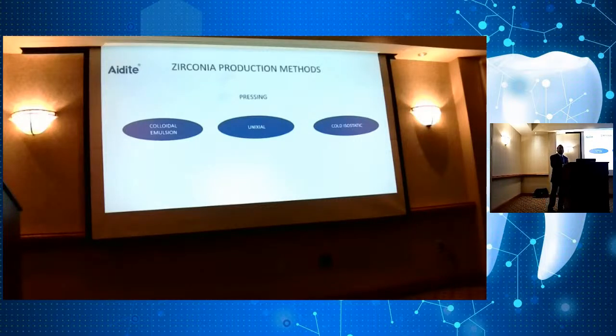There are some big inherent problems with colloidal emulsion. If the process is not accurate, you will get minute fractures and bubbles already in the green state. Okay. And so sometimes if you add colorants to it, it gets trapped in those little void areas. In my estimation, I don't think this is the best way to make zirconia, but it works. The next one is uniaxial pressing.